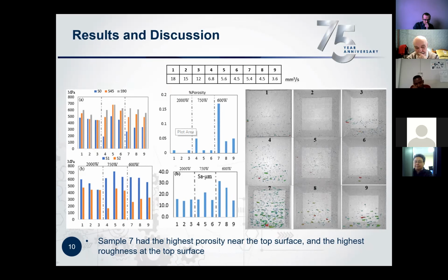But of course, in additive manufacturing, there are other factors at play that can influence porosity. For example, your layer recoating consistency. If it's not consistent, you can have areas which are not covered. You'll have a bed that is not uniform, and then this is going to influence the melting mechanism, and you are likely to end up having some random porosity in your samples, which is one of the contributing factors in terms of random porosity in SLM parts.